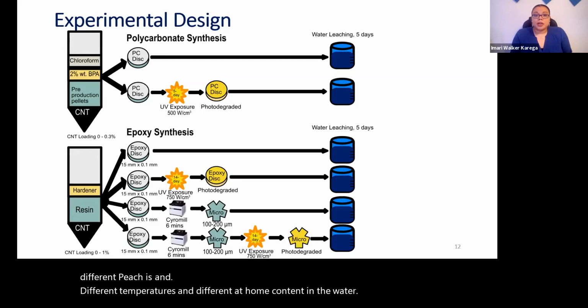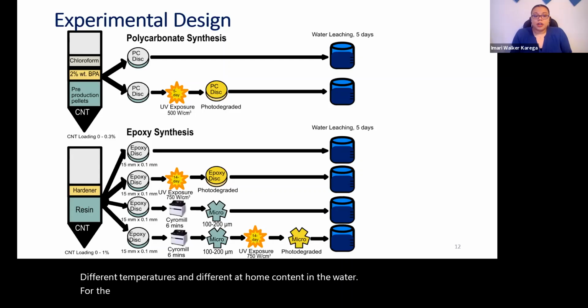For the epoxy, this was a hardener and resin mixed with carbon nanotubes at slightly higher concentrations, ranging from 0 to 1%.